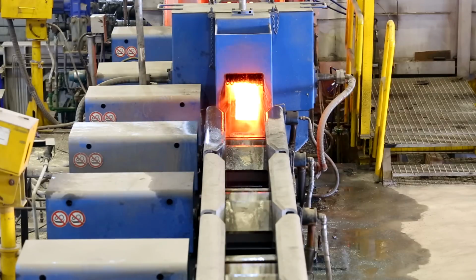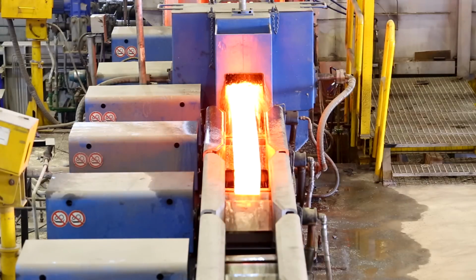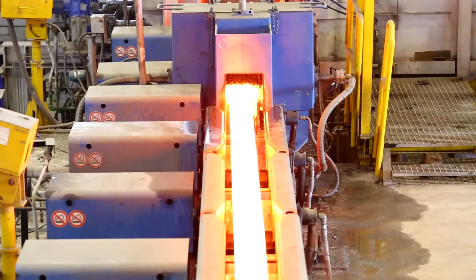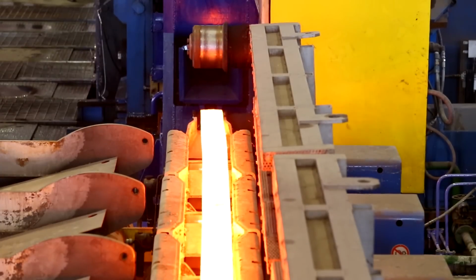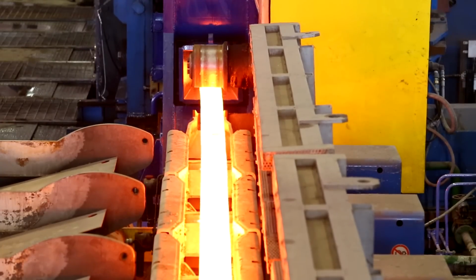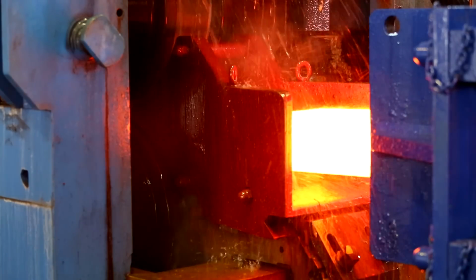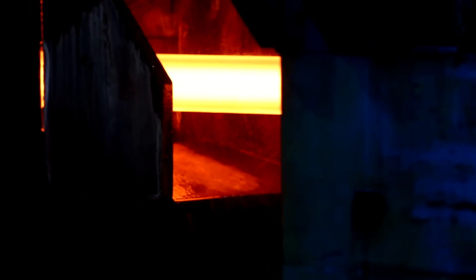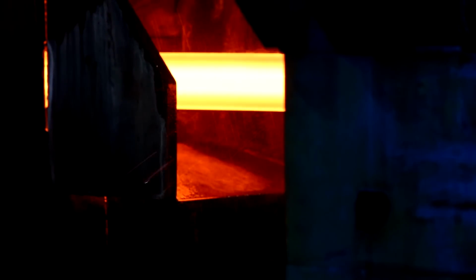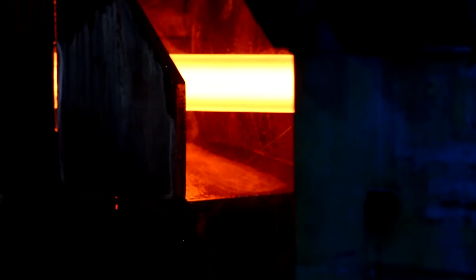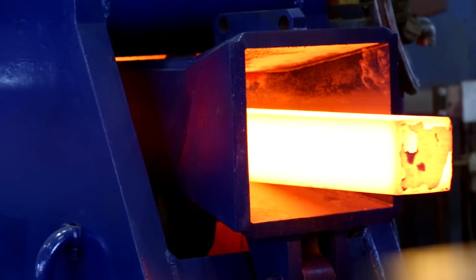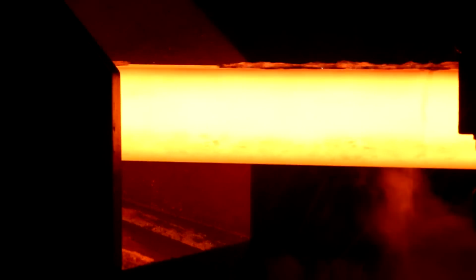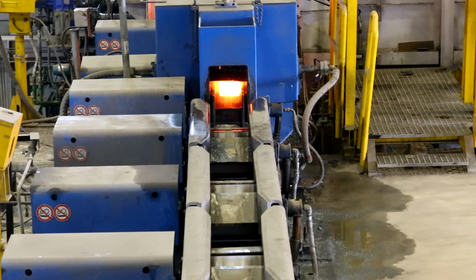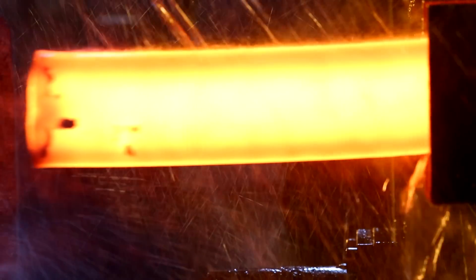At the exit of the furnace is a special descaler to remove scales from the billet's surface before it is rolled. The descaling process ensures uniform development of martensitic rim depth in the finished rebar, giving it high strength and ductility. Secondly, it ensures a uniform rib pattern of the finest quality, leading to the best possible bonding with concrete. As the billet enters the descaler, jets of water begin to spray the billet from all sides.